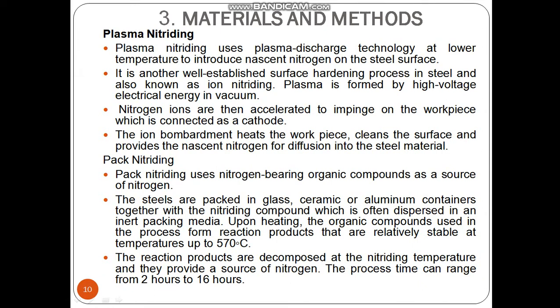Plasma nitriding. Plasma nitriding uses plasma discharge technology at lower temperature to introduce nascent nitrogen on the steel surface. It is another well established surface hardening process in steel and is also known as ion nitriding. Plasma is formed by a high voltage electrical energy in a vacuum. Nitrogen ions are then accelerated to impinge on the workpiece, which is connected as a cathode. The ion bombardment heats the workpiece, cleans the surface and provides the nascent nitrogen for diffusion into the steel material.